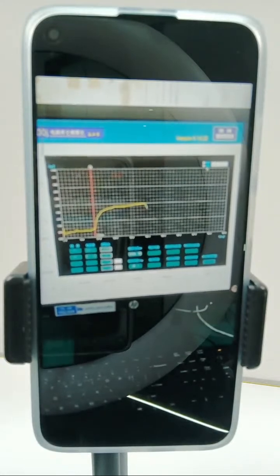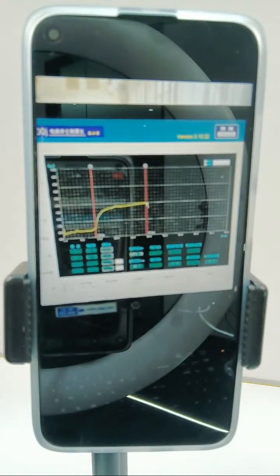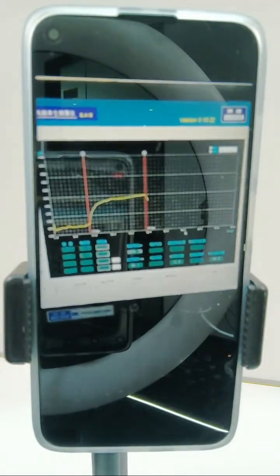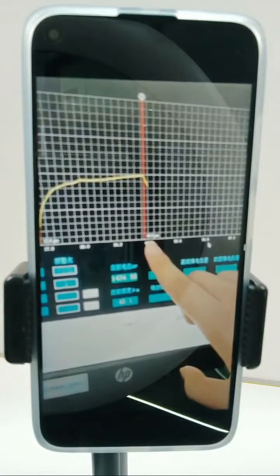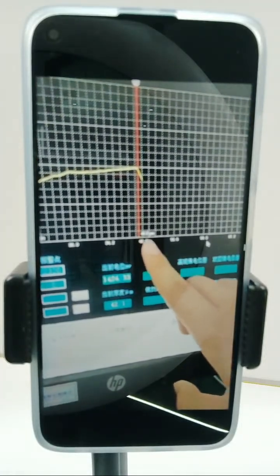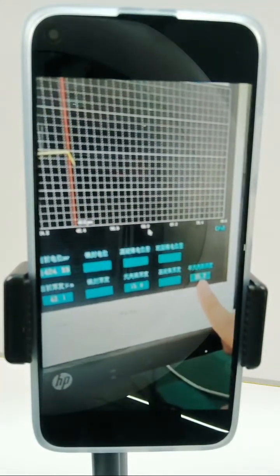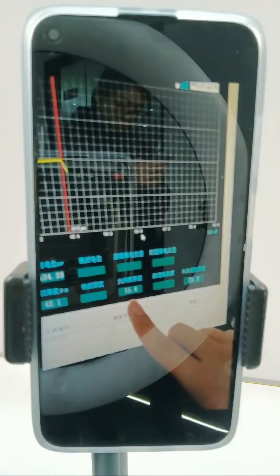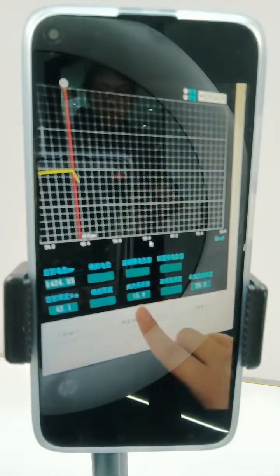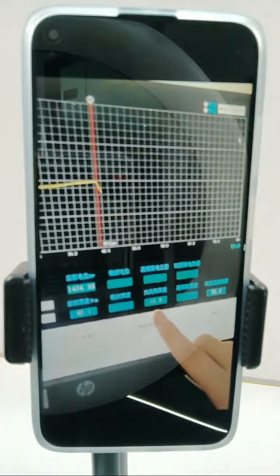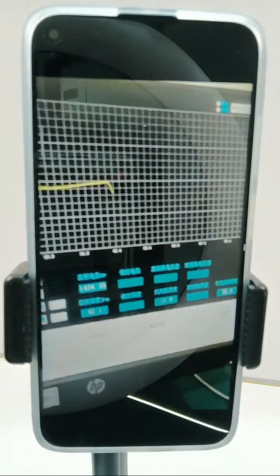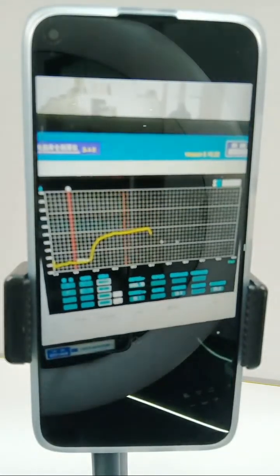Now we can read the data. Our workers are now choosing the data. We first choose the lowest point and the highest point to see the thickness. And we can see on this computer, the whole thickness is 40.8 micrometer. And the CMOS bright nickel layer thickness is 25.2 micrometer. And the bright nickel layer thickness is 15.6 micrometer. And the whole thickness is 42.1 micrometer. And later we can read the standard.